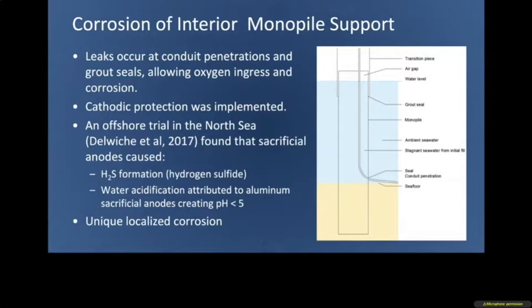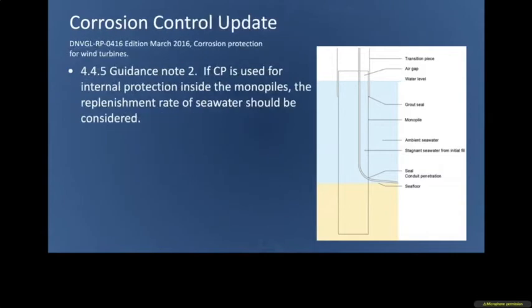The initial response to that was actually to place cathodic protection within the inside of the structures. But in a paper by Delwiche in 2017, he found that the chemistry of the seawater within these structures caused hydrogen sulfide to form and also created water acidification. And this in itself then created other unique corrosion problems. So in the corrosion control update, one of the guidances is that if cathodic protection is used for the internal protection of the inside of monopiles, the replenishment rate of seawater should be considered, which means now they're accepting the fact that you really need to create some porosity within the structure. So that's a very brief and quick outline of corrosion of the monopile structures.